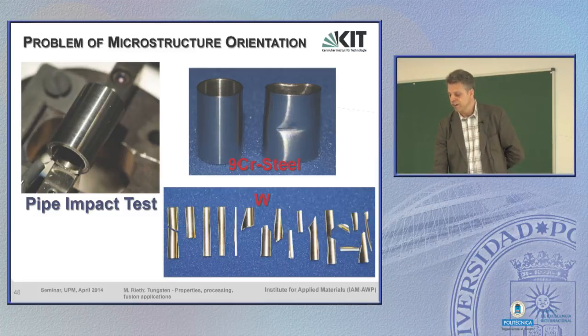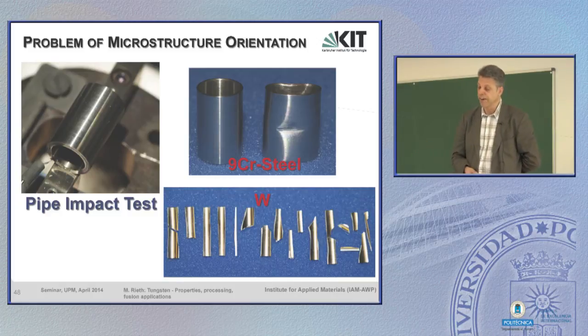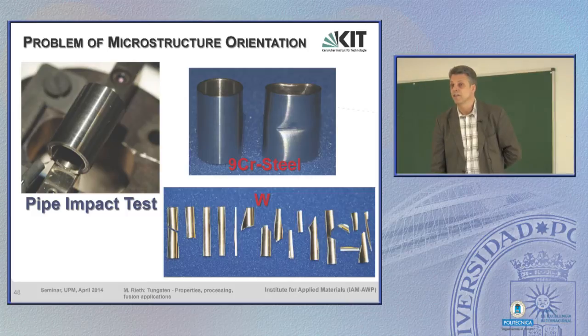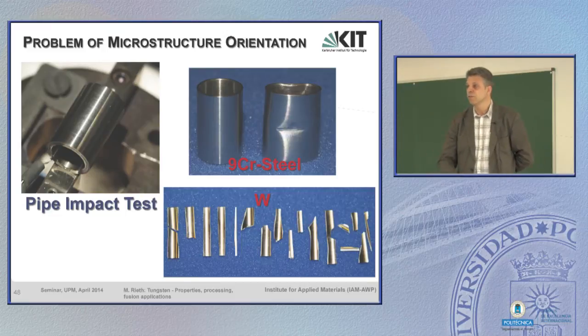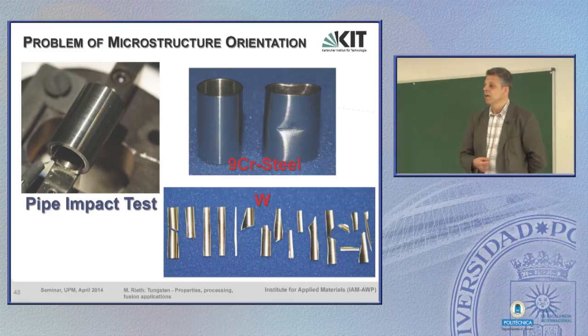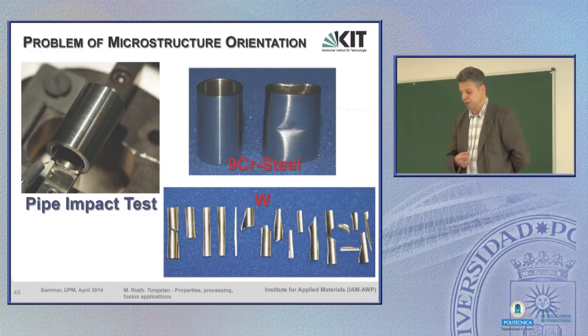You can do this with steel. We have put this small pipe of steel in the Charpy testing device, and the hammer deformed this piece of pipe, and you don't see any fracture. This is what a structural material should behave like. If you do the same with a tungsten rod, you unfortunately end up with several pieces of shards.